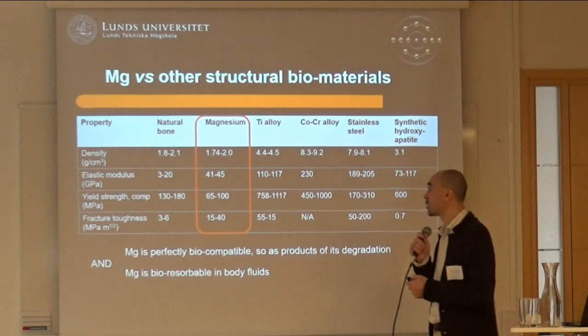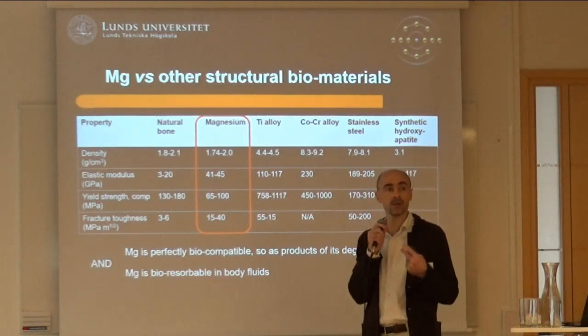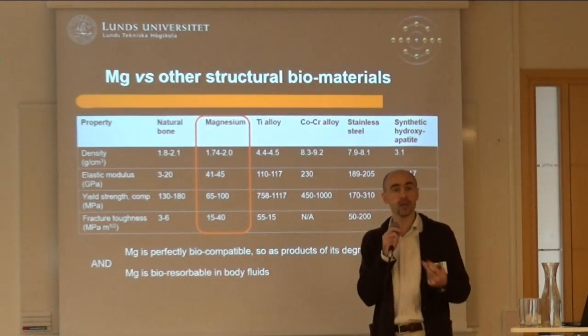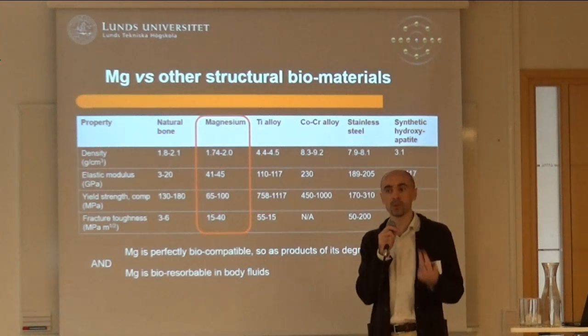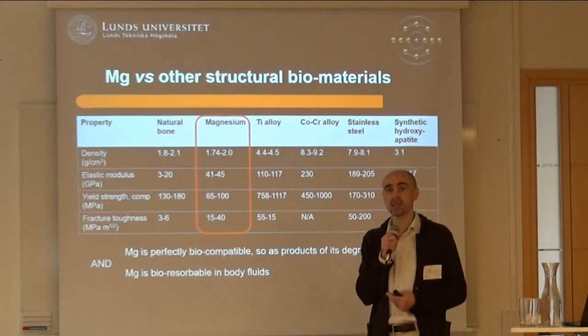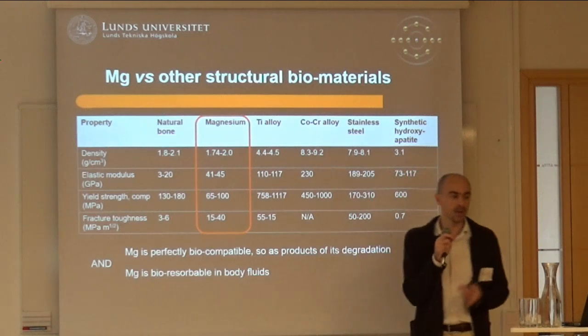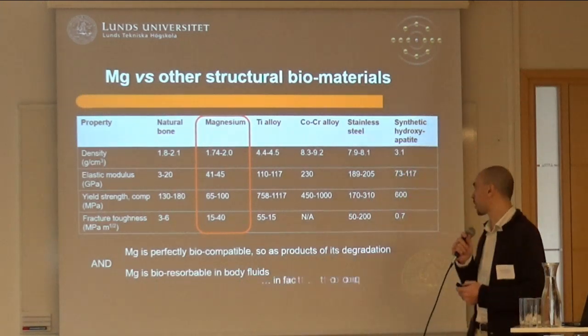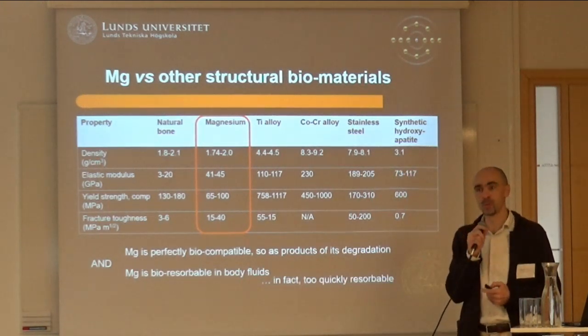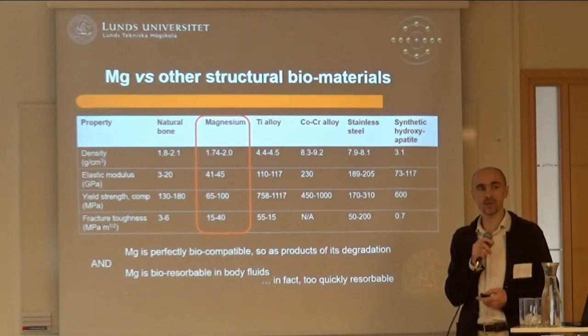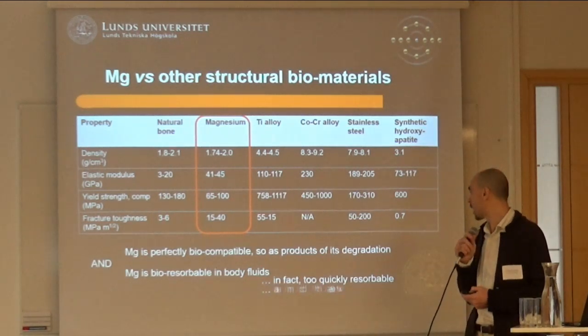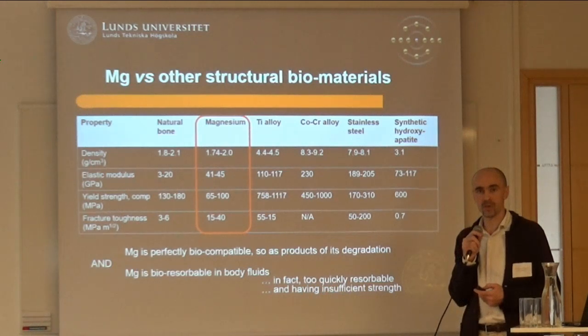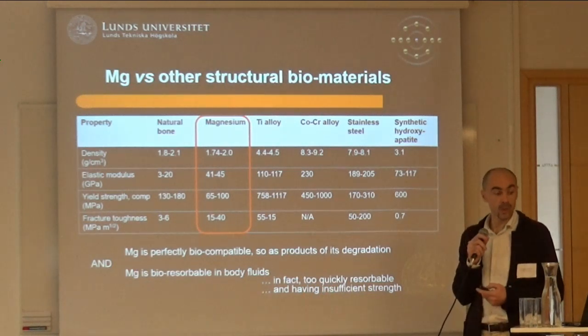Unlike titanium, for instance, if you have a temporary implant, you put it in the body once, and then it gets dissolved by the time the bone gets healed. You don't need to have a second surgical invasion. Beautiful. There are a couple of issues. It is resorbable too quickly, so we need to control the rate of corrosion or degradation, and we need to improve structural efficiency. So we are working in these directions.